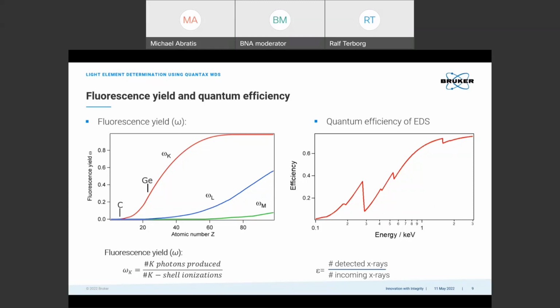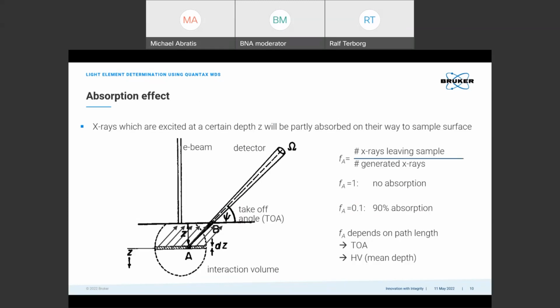On the other hand, light elements are defined as elements with the atomic number below 11. That applies to hydrogen and helium, which is not visible in EDS or WDS, and then lithium, beryllium, boron, carbon, nitrogen, oxygen, fluorine. Also, neon is included, but neon is normally not found in samples. If we have a look at the K-line energies of these light elements, they are all in the low energy range, below 1 keV, so that fits together.